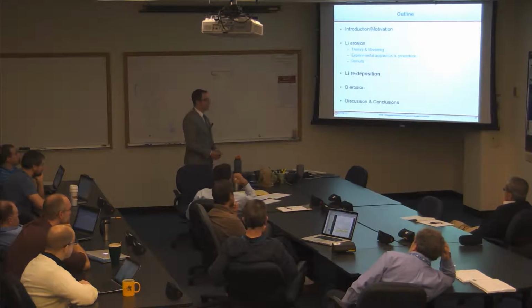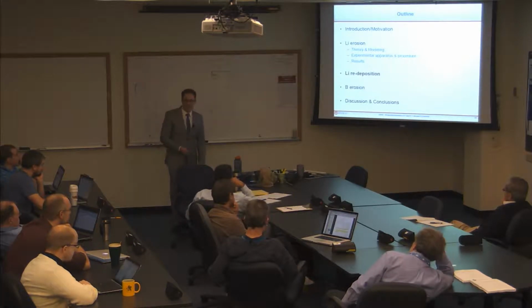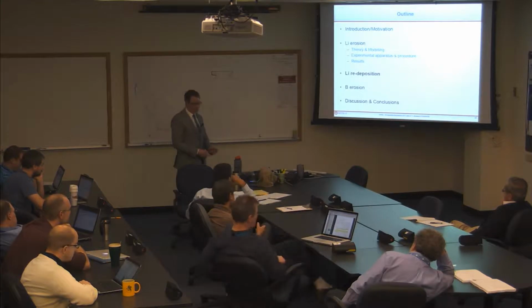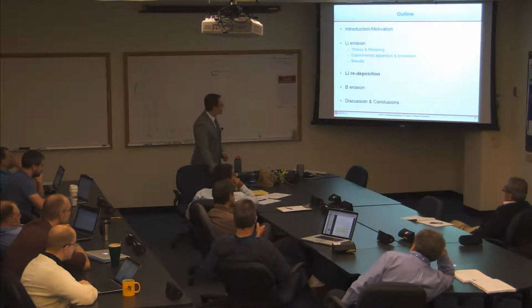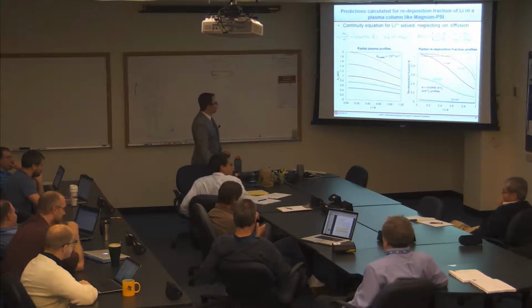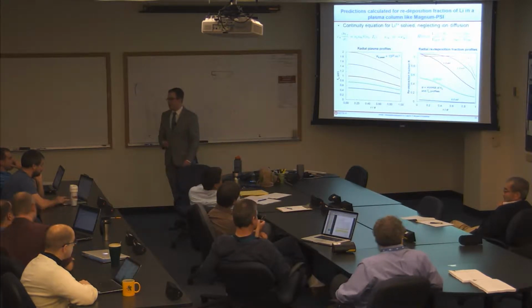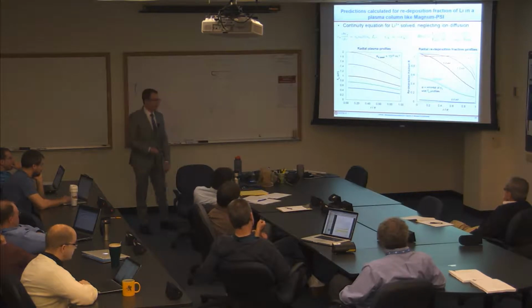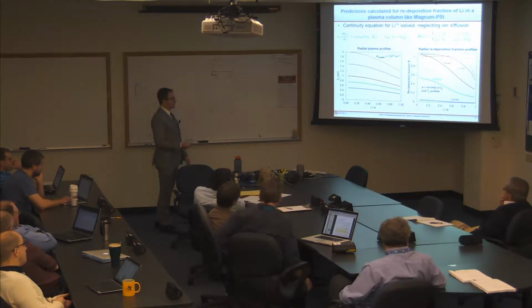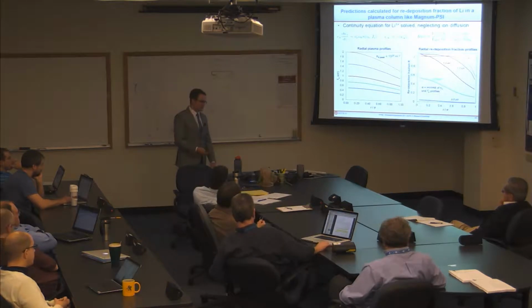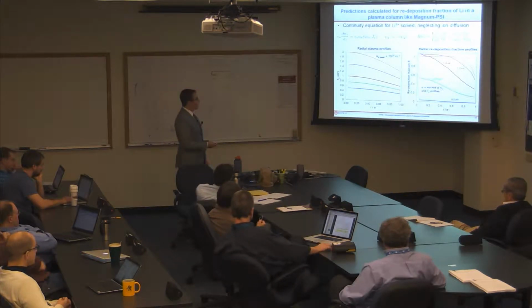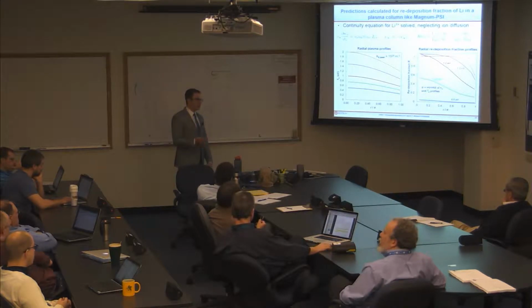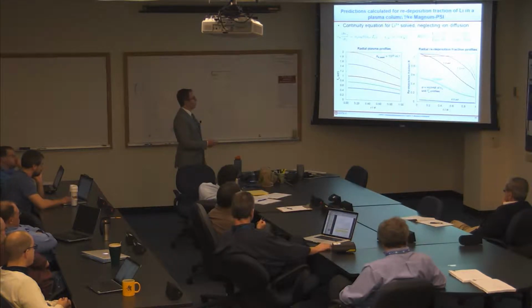Okay, so we have finished with lithium erosion, and we are moving on to lithium redeposition. So this is only 2 slides. So lithium redeposition, as I mentioned before, is a process where a lithium atom is eroded into the plasma, it ionizes, and then it goes back to the surface as it follows the magnetic field lines. So you can infer lithium redeposition fractions, which is the probability of the lithium atom redepositing when it's eroded off, by solving the continuity equation for lithium 1+. So that looks like this.